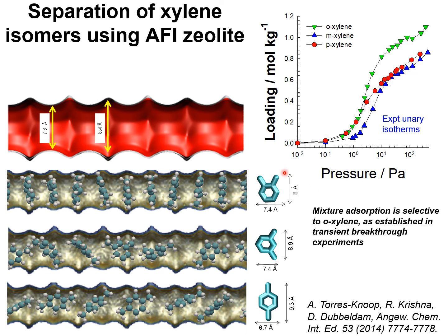Orthoxylene has a size that fits nicely within the grooves, and the packing of the molecules is face-to-face and within the same channel length, a total of 10.5 orthoxylene molecules can be located.